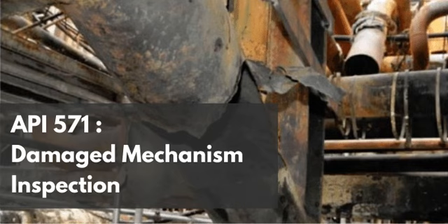But once that lean amine contacts the sour hydrocarbon gas, it absorbs the H2S and CO2 and becomes rich amine. Yes, it is chemically saturated. And the API text states that equipment in rich amine service is actually less susceptible to cracking than equipment in lean amine service, which is crazy. Why does loading the fluid with highly corrosive acid gases actually protect the carbon steel from this specific cracking mechanism?